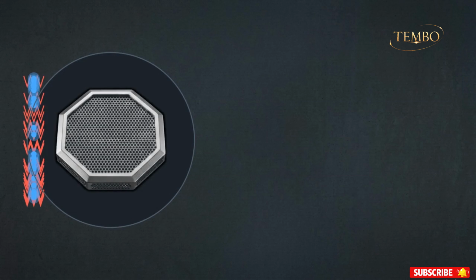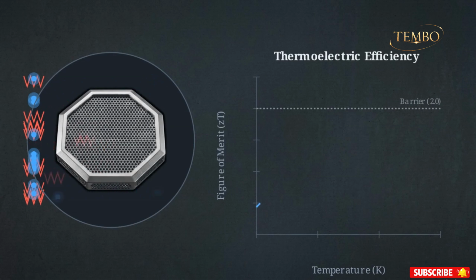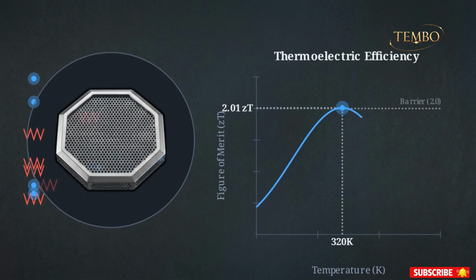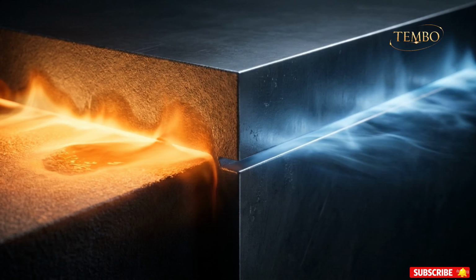These structured boundaries act as a physical sieve, scattering backward-moving heat phonons while allowing electrons to glide cleanly. This efficiency spike is shown by the data curve rising sharply, breaking past a peak ZT of 2.01 at 320 Kelvin. By physically engineering the seams between microscopic grains, researchers successfully trapped the frictional heat without choking the electrical current.